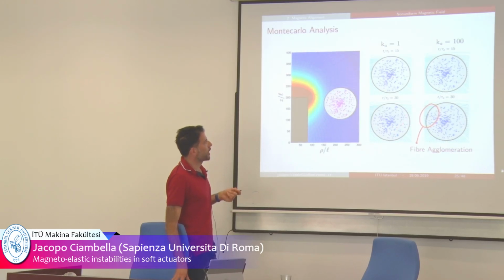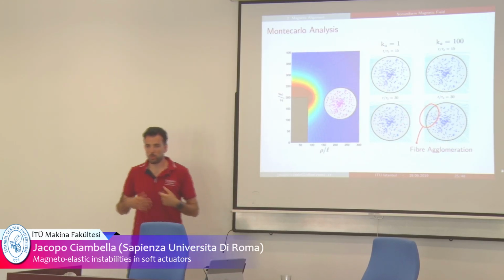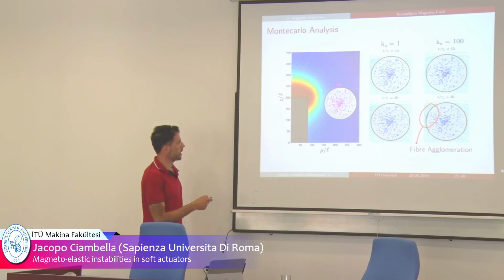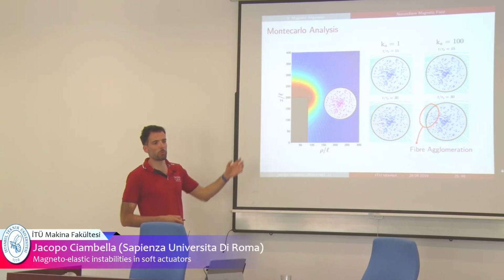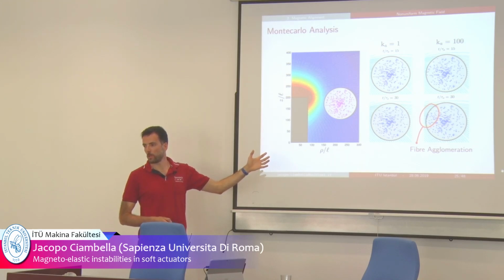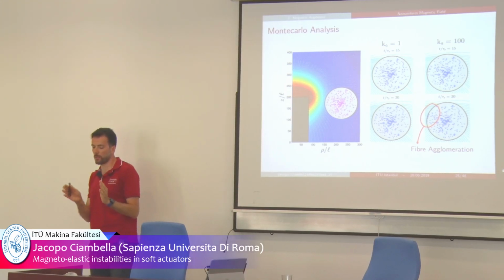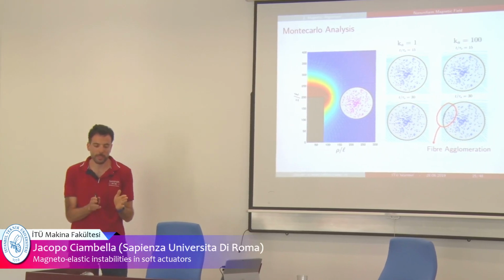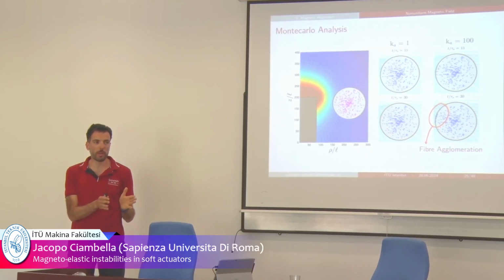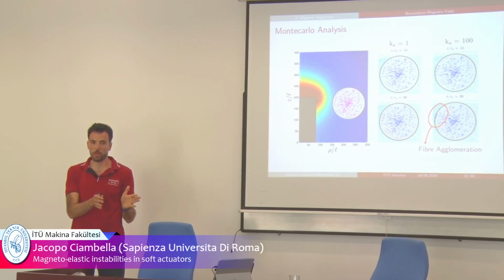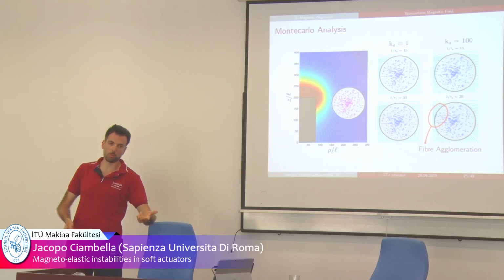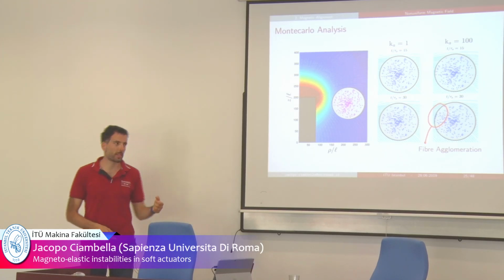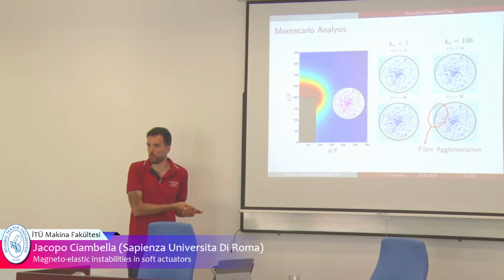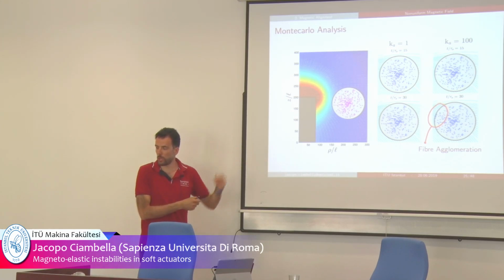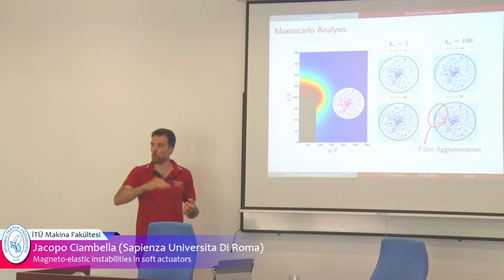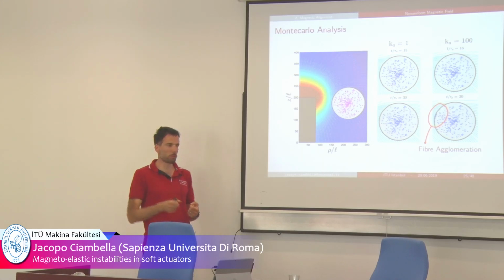Then we do Monte Carlo simulation, so we put a lot of particles here because this is to reproduce our experimental setup. The advantage of using an electromagnet is that within the poles of the electromagnet, the magnetic field is uniform. And by controlling the current, you can also control the intensity. With cylindrical magnets, of course, you cannot control the intensity, but you have nonlinear fields, so you potentially can bend the fibers within your specimen.